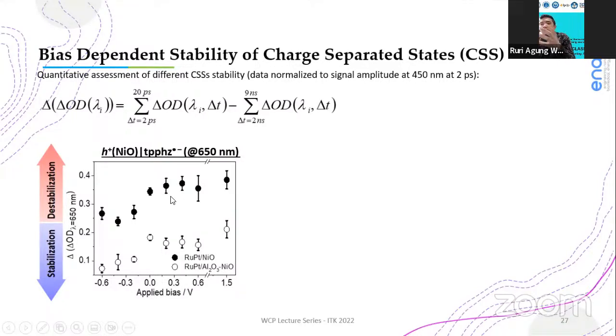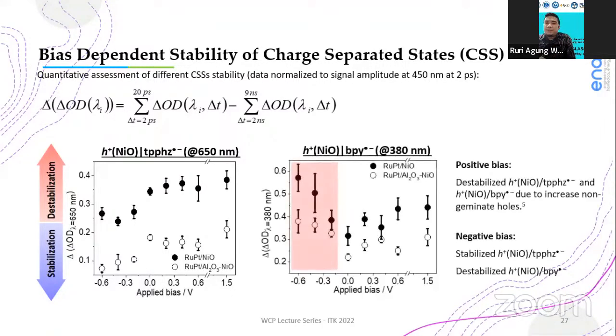And this is plausible, because if we apply positive bias, then we will increase the non-geminate holes on the nickel oxide. We put more holes on the nickel oxide, and then recombination becomes more probable with radical anions. But at negative bias, what happens? At negative bias, we expect the charge separated state will be stabilized, since we extract all non-geminate holes from the nickel oxide surface. As we can see here, the result shows that it's true for the TPPHZ, it becomes lower, it becomes stabilized. But why for the bpy does it become destabilized? It's increasing at more negative bias.